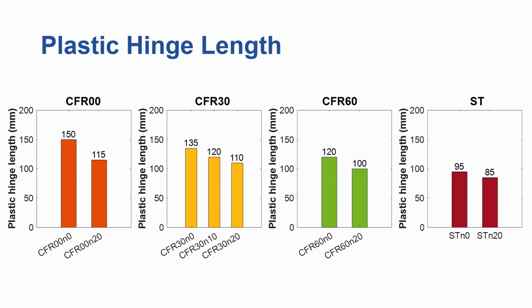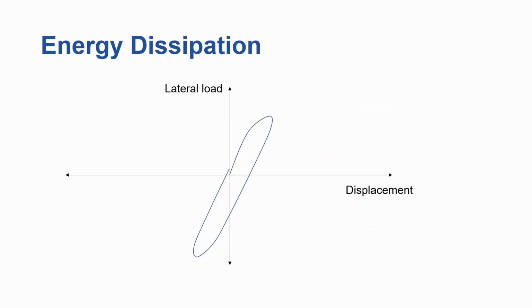So we notice a similar trend. As the axial load level on the specimens increases, the plastic hinge length reduces. And another thing is, as the rubber content in the concrete infill increases, the plastic hinge length reduces slightly.